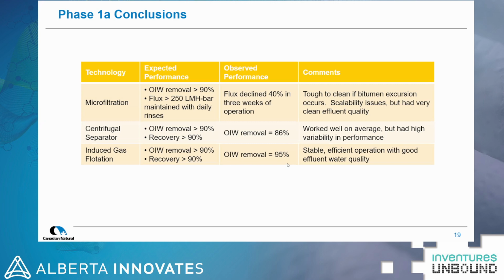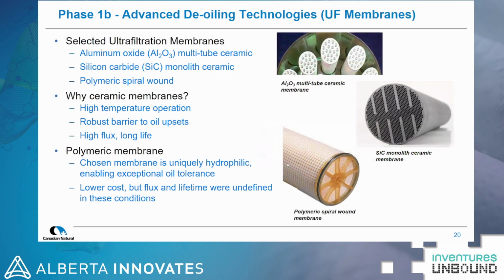So after that, we moved on to trial the advanced de-oiling technologies, the ultrafiltration membranes. And we used the IGF to feed as upstream pretreatment for the ultrafilter membranes. So we selected two ceramic membranes and one polymeric membrane. We used an aluminum oxide multi-tube ceramic membrane and a silicon carbide monolith ceramic membrane. Why ceramic membranes? They're suitable for high temperature operation. They're robust. They provide a robust barrier to oil upsets. You can operate them at high flux, and you can get long life out of the membranes as well.